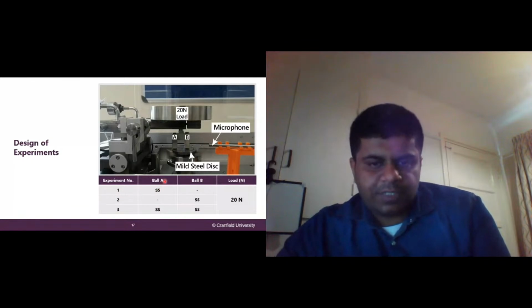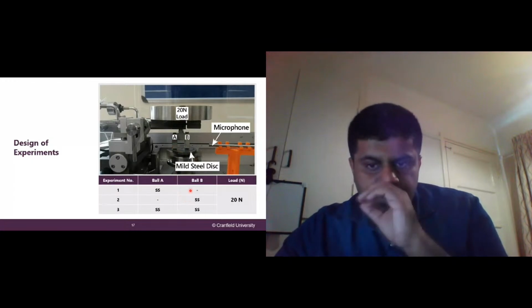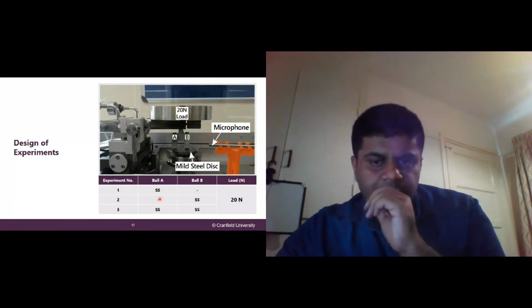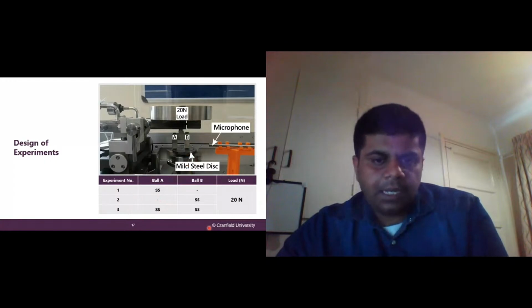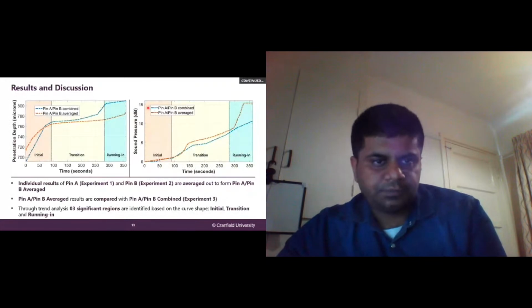These are the experiments that we performed. In the first, we took the stainless steel ball on its own. In the second, we took the stainless steel ball only in ball B and nothing in ball A. And in the final one, we took the balls in both the holder positions, and then we investigated the wear. So we took an average of these 2 values and compared it with this one to specify how the wear translates when you move from single point contact to multiple point contact.